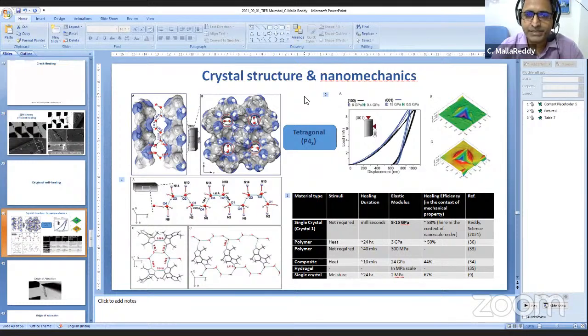So there is some dependence on the medium, but again quantification is a little difficult, but we see a clear difference when you go from one end to the other. If you take highly polar and non-polar solvents, we see some difference. Again, doping is another interesting question. If you can dope and create more imbalance, then the way it breaks and the amount of plasticity you can get in your doped system, all these will be very interesting.